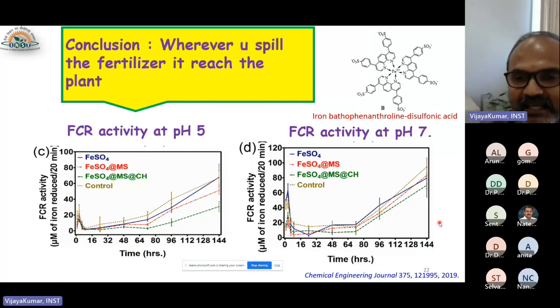ferric chelate reductase, FCR. This is expressed in the root when the root is in Fe negative solution. So we keep the root in Fe negative solution growth medium for like 20-30 days so that the ferric chelate reductase expression happens. And then we expose the root to all different composites of the material: FeSO4, FeSO4 loaded in mesoporous silica that is coated with chitosan, and then control. And here we were able to see that at pH 5 incubation, there is a very low expression of ferric chelate reductase. Thus we prove that our material is targeted to the root to release iron and feed the iron to the crop.